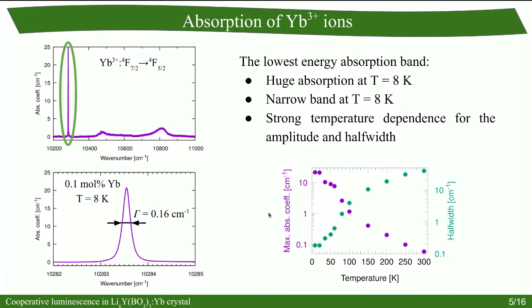First, I will speak about the absorption of the ytterbium ions in this host. Here you can see the absorption spectra of the ytterbium ions, which was measured at a low temperature of only 8 Kelvin. The main absorption band, which is the narrowest of these three absorption bands, has a very big amplitude at low temperature. However, this absorption band also shows a very big dependence as a function of the temperature, which is demonstrated here.